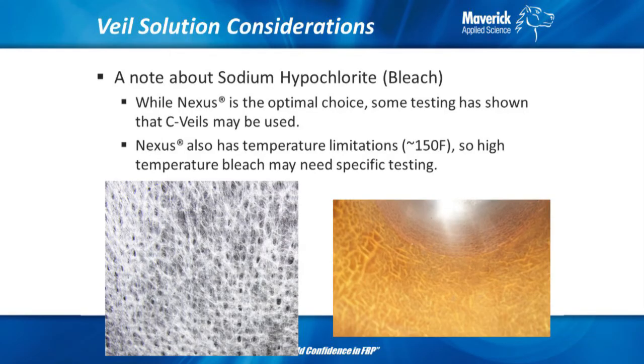So again, if you can put a coupon in your process, that is a much better way. Part of the study I did comparing Nexus to C-Veil was coupons in actual storage tanks, and I've got a paper that I've written on that. Showing the data, when we did the testing at 150 degrees with sodium hypochlorite, after 12 months the Nexus coupon only had 30% retention of properties, where the C-Veil coupons had 70% retention. So there is information available. You have to know who to ask and where to find it. You have to go searching for it sometimes.